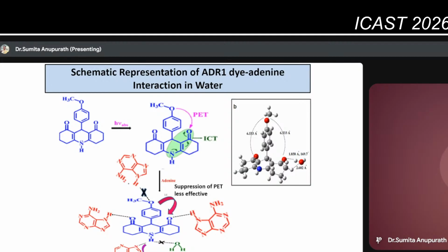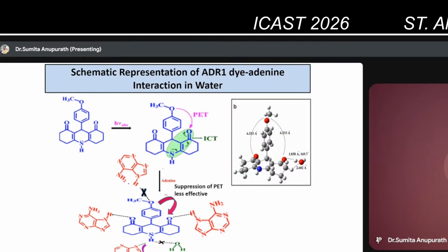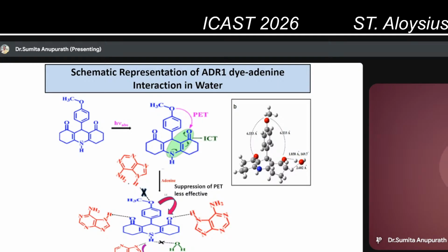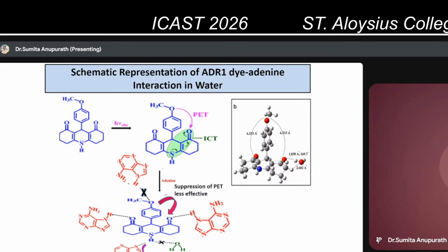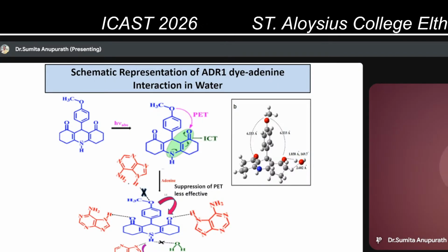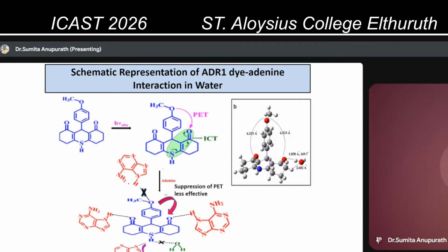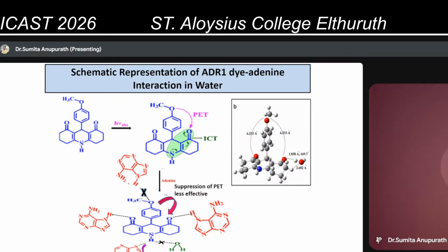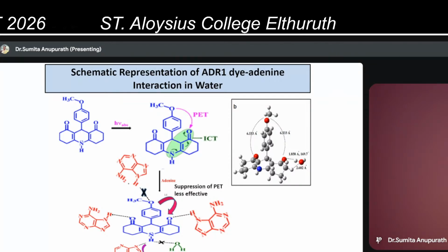So we can say that suppression of the PET process is less effective when compared to other molecules. But at the same time, when we had carried out a similar study with urea, it was found that the PET process was completely blocked and there was a much better fluorescent enhancement.